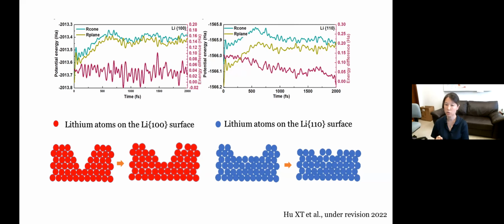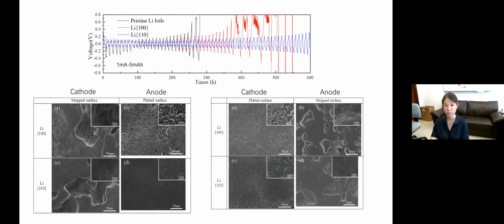This is the take-home message: in many cases we look at the plating, or we focus on the growth process of the lithium on the substrate. But here the idea is that when the surface roughness is created, it can be created during stripping, it can be created during plating, but once it's there, the lithium 110 surface actually has the tendency to flatten out by itself, but that does not exist in other surfaces such as the lithium 100, right? And that's probably the so-called thermodynamic origin of why the lithium 110 surface is a better one, right?